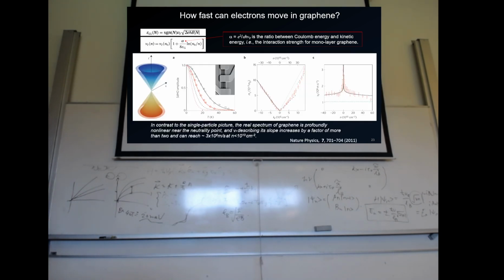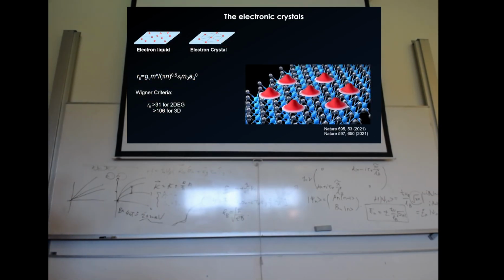So it's not a new phenomenon. It has been studied. Yesterday we mentioned to you that if you suspend graphene, except for the very clean quality and very high mobility you get, you can also enhance the interaction at the vicinity of the Dirac cone, at the Dirac point. And as a result, the Fermi velocity can be renormalized by a factor of 2 or 3, and that means the cone is even sharper. There is a logarithmic interaction in the system, and it's been studied both theoretically and experimentally in 2011. So that's a very early result showing that by just suspending graphene, by diminishing the denominator, the dielectric constant of the environment, you can enhance the interaction between graphene electrons, and you can make the velocity higher in the system. And this is the hint from the literature.